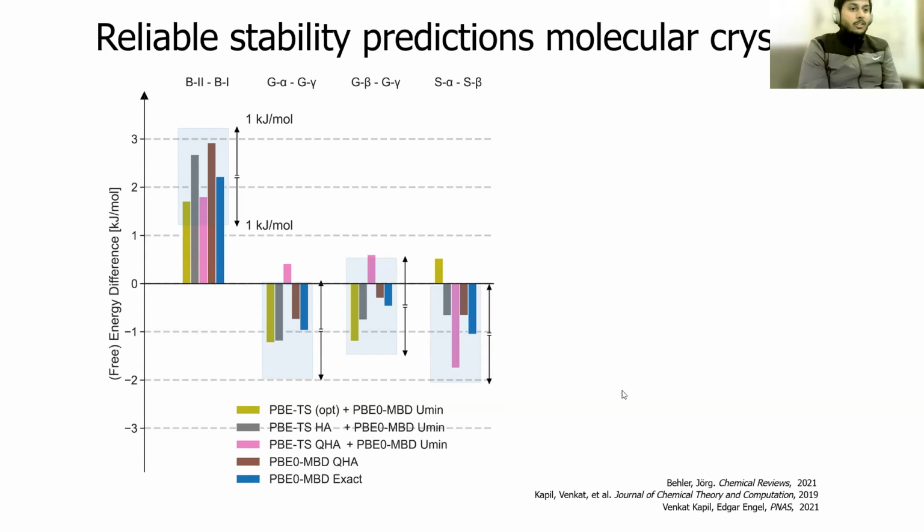And yeah, we saw that we got a very good agreement with experiments in all of these cases. And again, because we did not make any approximations in our sampling, any disagreement with the experiment can be traced back to the potential energy surface. Unlike some other approaches, like if you take a harmonic approximation, you may not be sure whether the disagreement arises because of the harmonic approximation or the density functional.